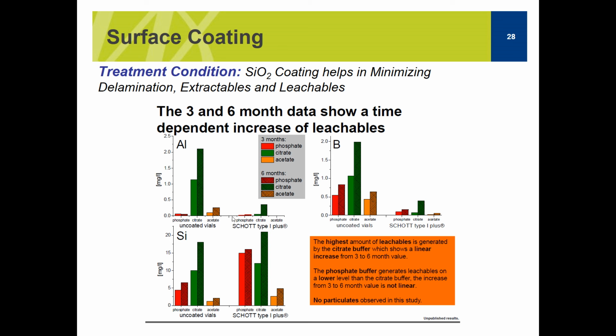Okay, and then basically they stored them for 3 to 6 months with 3 different buffers. The buffers they used are phosphate, citrate, and acetate, and they stored them again for 3 to 6 months. So they filled the vial with these different buffers, let it sit, and I think it was at 50 degrees for 3 to 6 months. And then what they did is they checked for the different extractables and leachables. So they were looking for the different metals in this case.